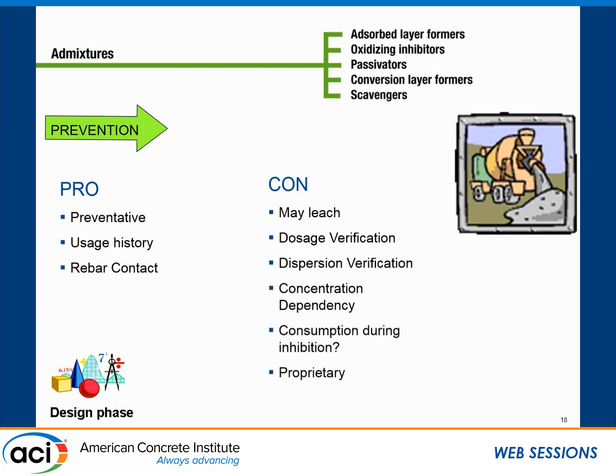However, do they stay in the concrete where you want them? Do they leach out? How do I verify the dosage? Trust the ready mix supplier, I guess. What about dispersion verification? Did they all get mixed in the way they should? Many of them are concentration dependent. That is, do I have enough of the stuff in there to really do me any good? Do they get consumed during their inhibition operation, such as nitrites? And they're proprietary. Us material suppliers don't really tell you a whole lot of what they are sometimes. There's organic and there's inorganic inhibitors.